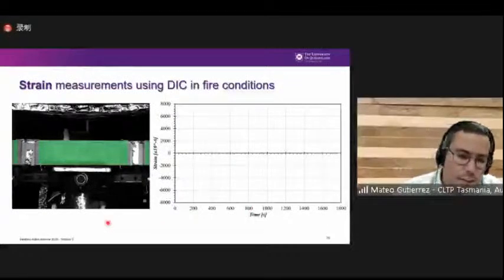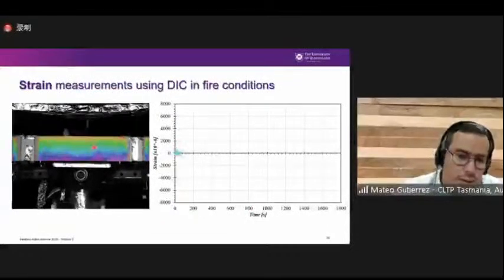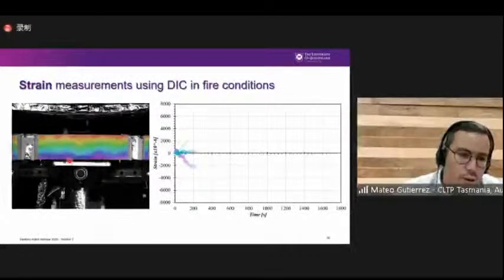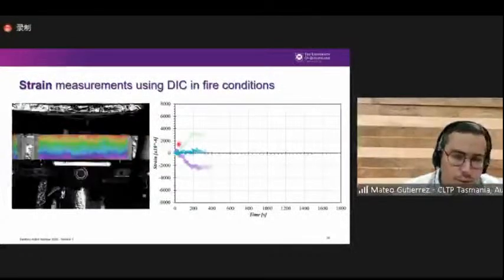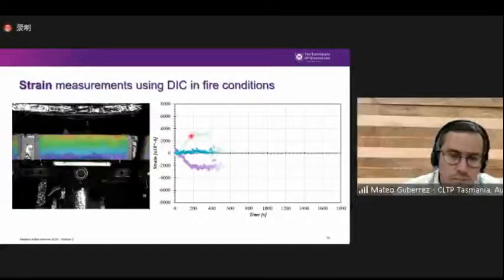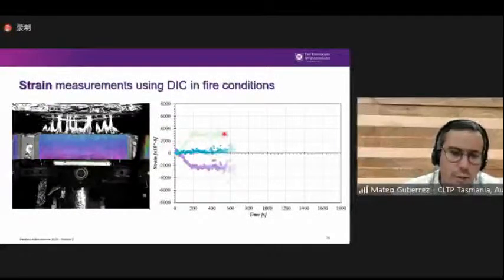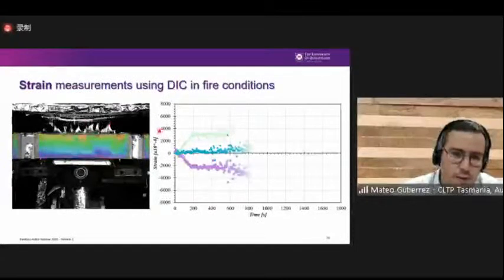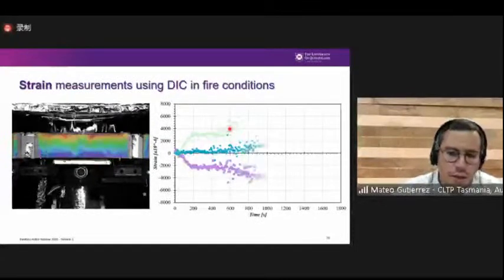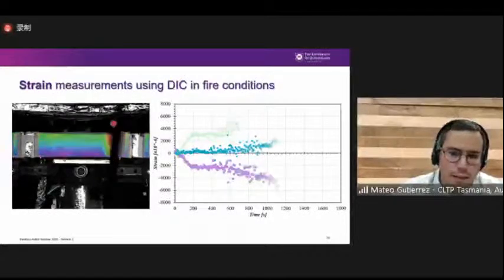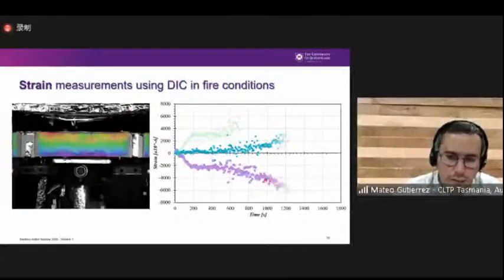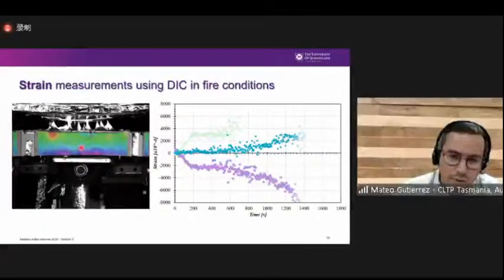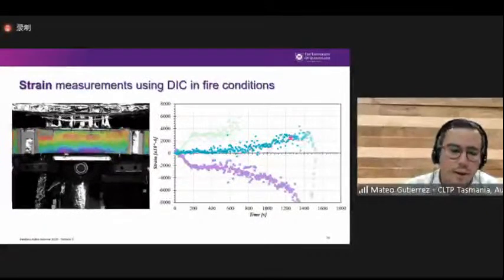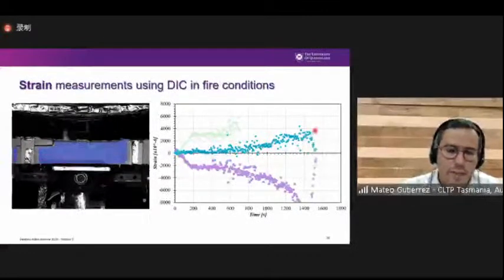So again, same process. We start loading the beam. We have compressions at the bottom, tensions at the top. We were loading the beam until the target load was reached. Then we start burning the beam. And once you start burning the beam, you have more strain in the tensile side, more strain in the compressive side. This was the strain at the neutral axis. And you can see some displacement of the neutral axis. And then you keep burning the beam until you reach the failure.